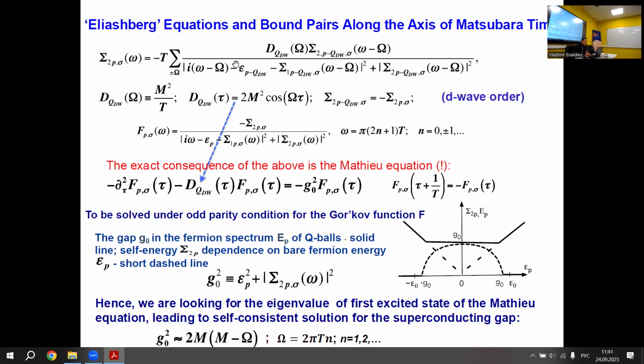And it proves to be that this equation, if you write down the Gorkov's anomalous Green's function in this standard form, in Matsubara, in Euclidean space, you can get that this Green's function with this Eliashberg-like equation exactly obeys the Mathieu equation of this shape. So this is exact result of this relation. So F, this is tau dependent Fourier transform in real space, but tau dependent anomalous Gorkov-Green's function. D, this is this expression because again we have Q-ball density wave which has only single Matsubara frequency omega, and G sub 0 squared, this is